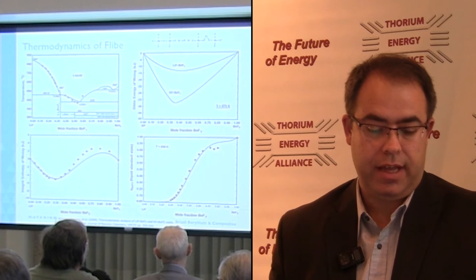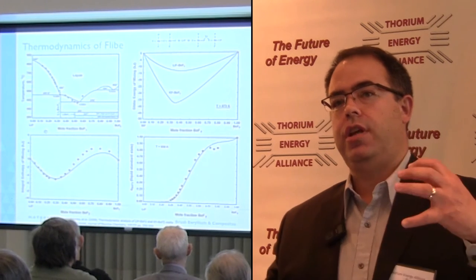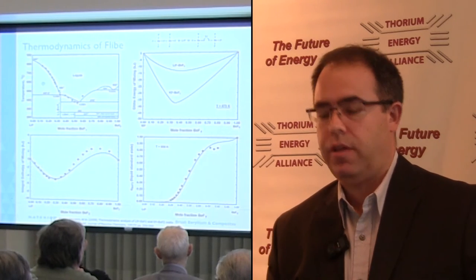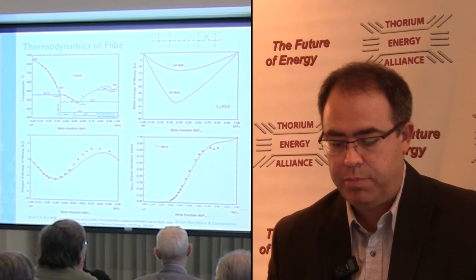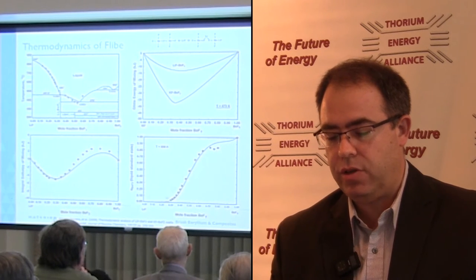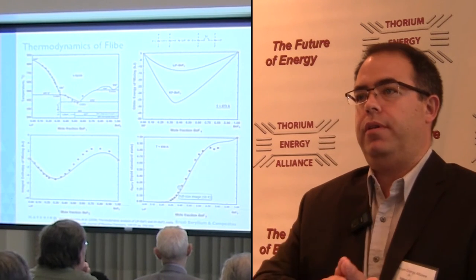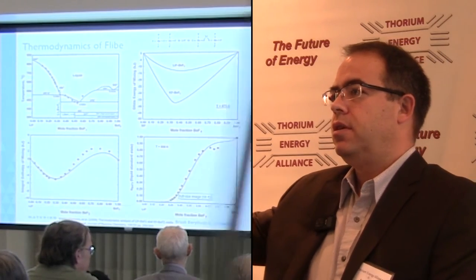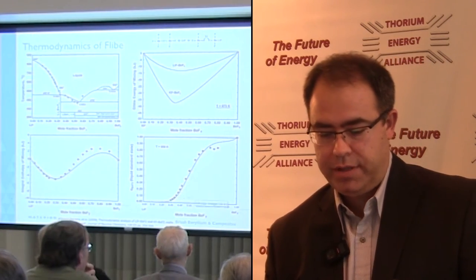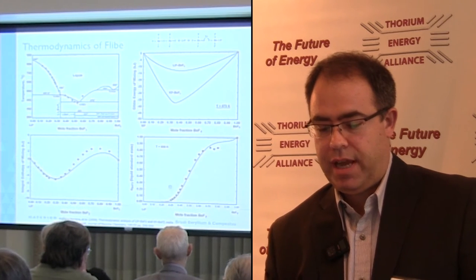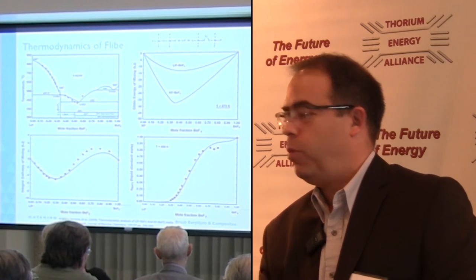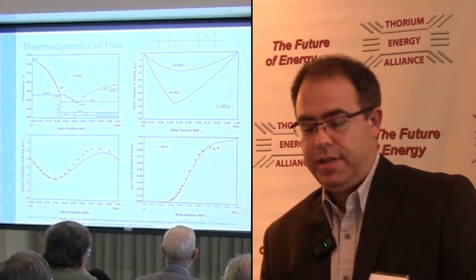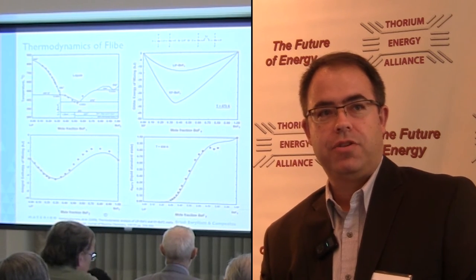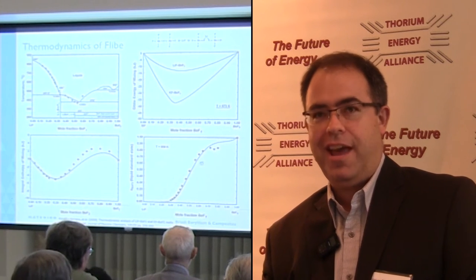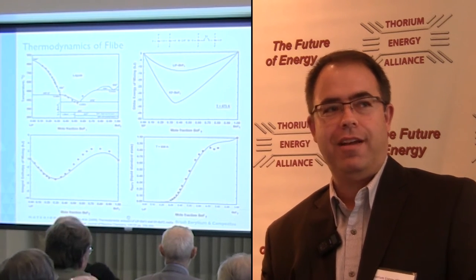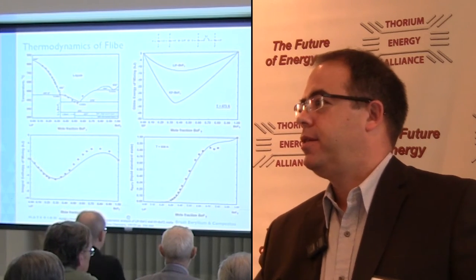We look at things like the enthalpy of mixing. How much energy do I release when I mix these things together? How much the activity of beryllium fluoride is, and that tells you what happens if I heat this up. Will the beryllium fluoride vaporize and diminish in my melt? Well, one nice thing about beryllium fluoride, the activity is actually negative, for those who like thermodynamics. This doesn't follow the ideal mixture law. It's a Henrian type solution with a negative deviation. And we'll have a quiz about this later today.